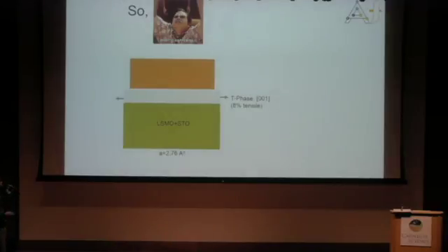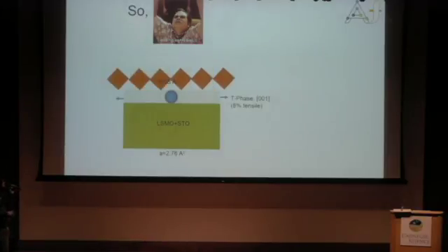Once there is strain relaxation, the incoming material should have a lesser in-plane parameter compared to this strained T phase. But there is a substrate constraint. So the way the system accommodates this is by rotating the crystals from 001 to 111. And when you rotate it, you still have a higher, say, lattice parameter. So what we need to do now is to apply some kind of compression.